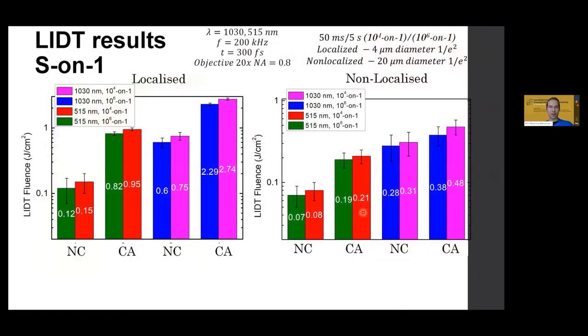And finally, some summarizing results. It may look overcrowded and messy, but it stands for two types of measurements, localized 4 micrometers and non-localized 20 micrometers, whether we focus into the lens or pass light through the lens. And for non-calcinated and calcinated objects, and two different wavelengths: visible 515 nanometer green light of femtoseconds and near infrared, the first harmonic of the Pharos laser, so 1030 nanometers, and two different durations, shorter exposure time of 50 milliseconds or 5 seconds. And basically in all cases, we see an improvement for the calcinated lenses.